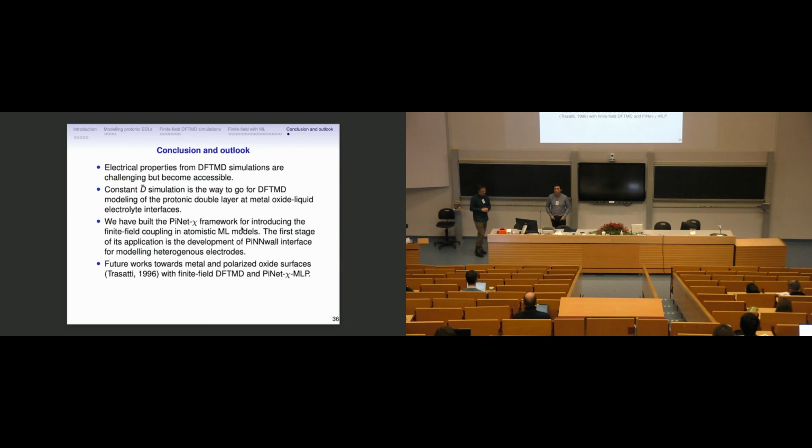Right. So there are two aspects to the answer. One is that when we build up double layers, we leverage classical molecular dynamics simulations to bring the ions closer to the surface. So this saves you a lot of time. And second, because you switch the electric boundary conditions, the relaxation time of the polarization is sped up. This is due to the so-called Debye series of dielectric relaxations, where Debye showed that if you switch from constant potential to constant charge, then the dipolar relaxation will speed up by the dielectric constant of the system. And for water, it's equivalent to a 2-order-of-magnitude speed up. That is the piece of physics we explored here to speed up the simulation.